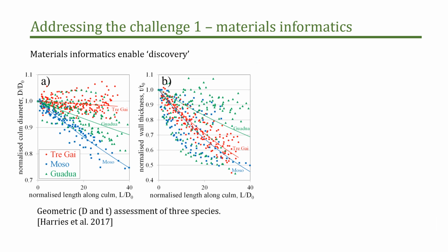A second example, which I found absolutely fascinating, was we were looking at 3 different species of bamboo. In this case, a thicker-walled Tregai material and thinner-walled Moso and Guadua materials. And we were looking simply at the geometry of these materials. And so what we have plotted here are the diameters of the materials, or normalized diameter of the material, excuse me, and the normalized wall thickness of the material. And as we can see, we've got massive amounts of scatter. That's not particularly surprising when we're dealing with bamboo.